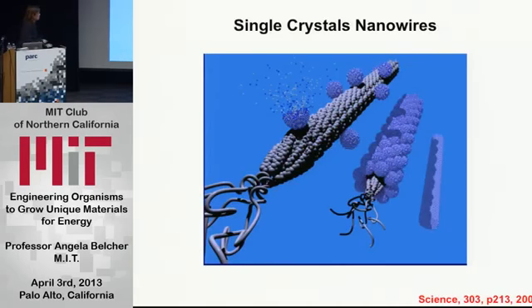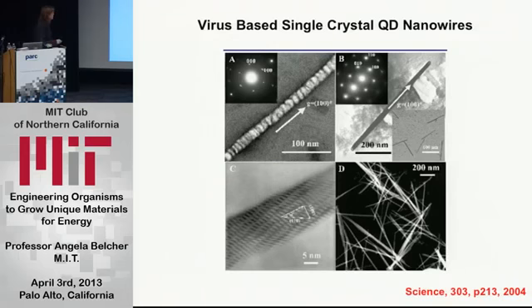And so, again, as a material scientist, this is an object that has a great aspect ratio. It's long and skinny. And if you can nucleate materials, you can think about nucleating polycrystalline materials, or materials that may be highly aligned, or single crystalline materials like in this case. And when we first did this, we were able to grow single crystal materials. This was for II-VI semiconductors. I think it was zinc sulfide and cadmium sulfide based materials. And we showed that you could grow polycrystalline materials. This is a TEM image. This is actually a dark field TEM image that are highly aligned. By heating at the time, we could grow single crystalline materials.